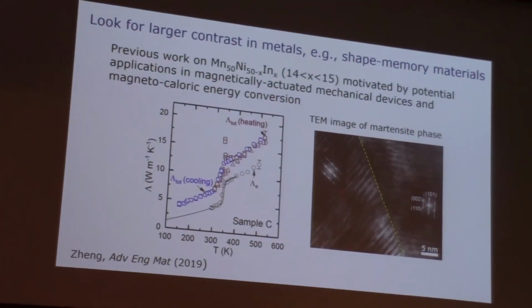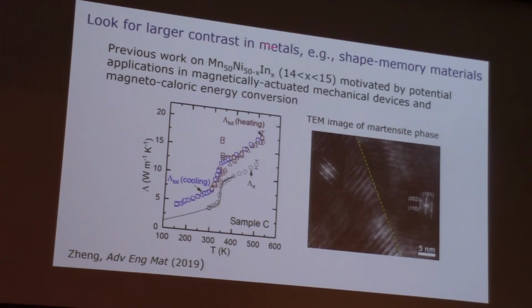Fast forwarding, this is the best thermal regulator material we have so far, that we've been able to come up with in the group. And this is a shape memory alloy. It's a ferromagnetic shape memory alloy. It's actually a known material. It's very sensitive to this composition of indium. It can also be done with tin.